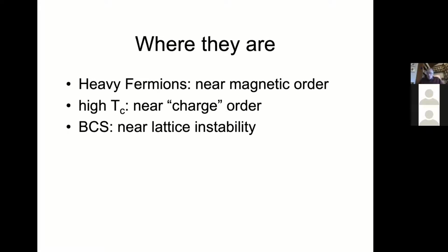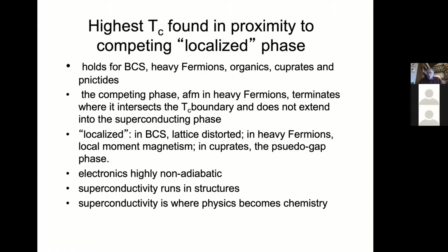So where are the superconductors? Well, for the heavy fermions, they're near magnetic order. For high TC, they're near what I would call charge order, this valence electron precise compound type material. In BCS, near some kind of lattice instability. So the highest TC is found in proximity to competing localized phases, quite generally across all kinds of materials, as I would say.